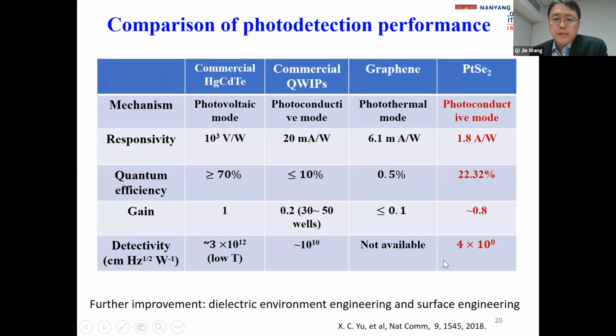And here I show a comparison with other technologies compared to graphene. The responsivity is significantly increased, and it also has a large quantum efficiency. The detectivity of the device is not as good as the commercial MCT or HCT. However, such detectivity result is measured at low temperature, and this is the room temperature measurement. I would say if this HCT is measured at room temperature, then they have similar performance. And further improvements can be carried out to improve the performance of the device, for example, by changing the dielectric environment, and also by doing surface engineering or using heterostructure 2D material.